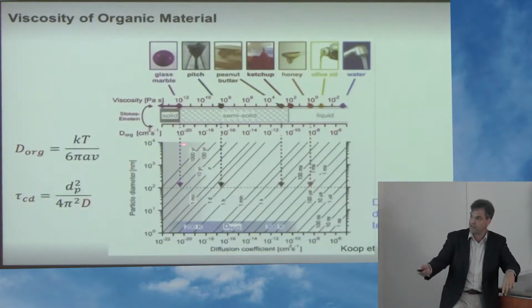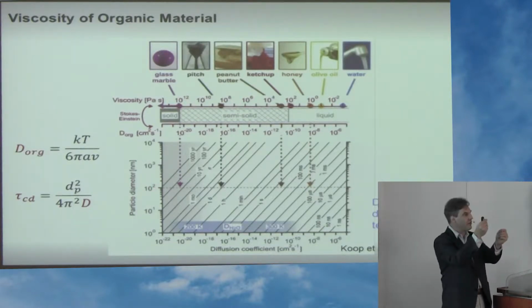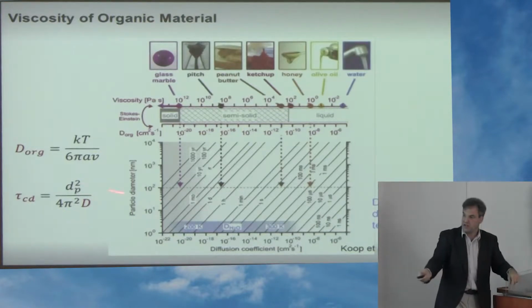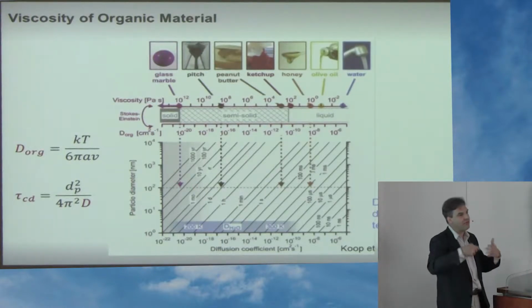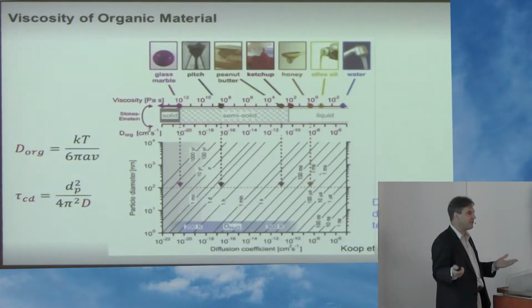So if you have this scale, you have a diffusion coefficient, meaning, okay, in a liquid, how long does it take for a 100 nanometer particle to transport a molecule through this 100 nanometers? If it is glassy, you can use the Stokes-Einstein equation, and it can take 10 years. So under atmospheric lifetimes, it will never mix this particle.